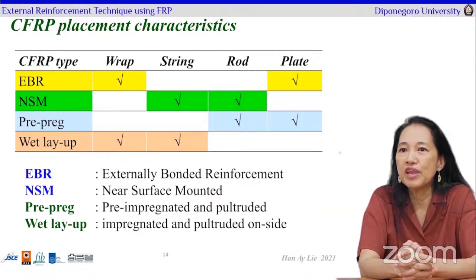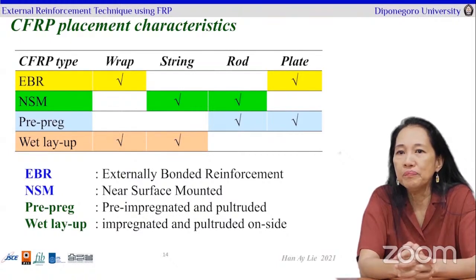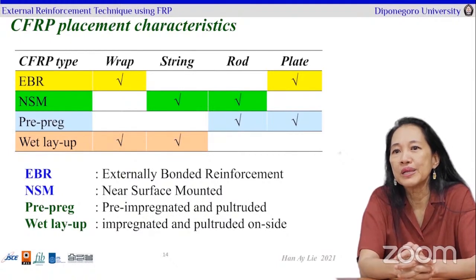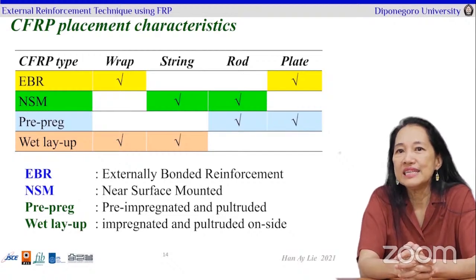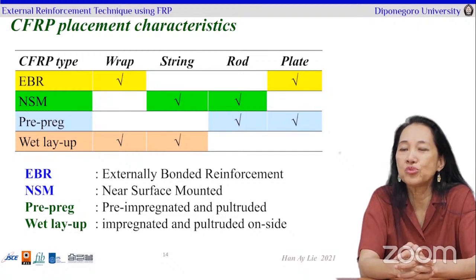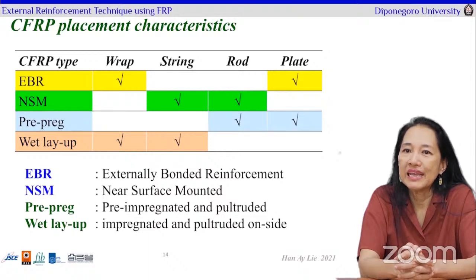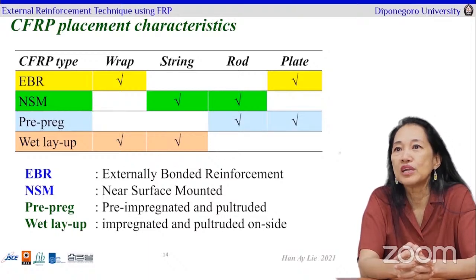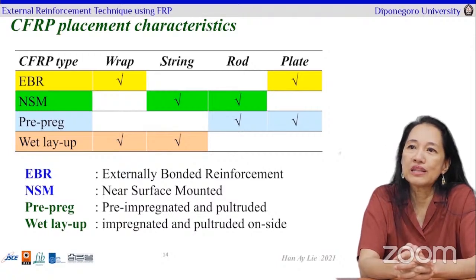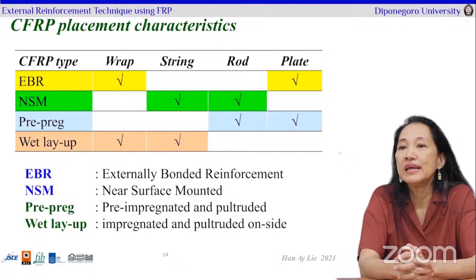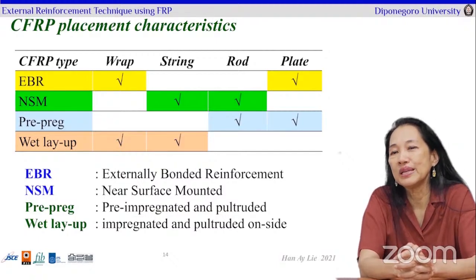For the system, we have pre-impregnated and pultruded, we call it pre-preg, which means that the fibers, like you saw before, were impregnated and pultruded in the firm, but with wet layup, we do it on site. You can see that for the wrap and the string, they were impregnated on site, but for the rod and the plate, it was factory made. So that's why they were much stiffer than the wrap and the string when they arrived on site.